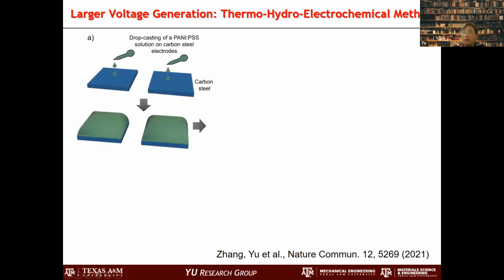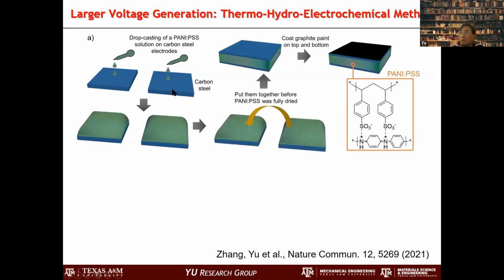In this case, we made polyaniline PSS, which is a copolymer. We made this polymer and then drop cast it on carbon steel. This is carbon steel, it is metal. And this greenish color is the polyaniline PSS. This is acidic, which means that it will corrode the carbon steel. So this is basically PANI PSS right there. And then we try to add another effect called the electrochemical effect. Because of the corrosion, there are additional effects. It's very simple: we combine them together, we sandwich them.